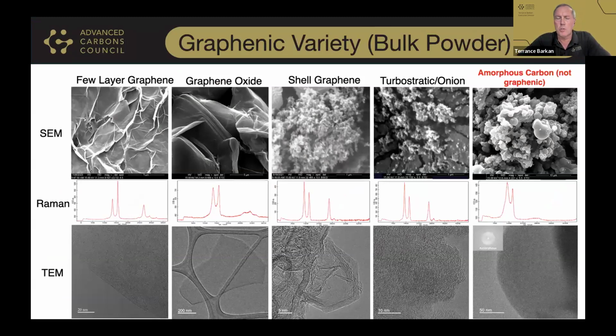And often when people hear the term graphene, they may not be entirely familiar with the fact that this is more like a family of materials rather than a singular specific material. Graphene can include sp2 bonded carbon that's in a single layer up to 10 carbon layers. On the left you have an example of a few layer graphene platelet. There's also a material referred to as graphene oxide, which has a high percentage of oxygen content, 30 to as much as 40% oxygen, which changes the behavior of the material significantly. Graphene, of course, is noted because it's highly electrically conductive, but graphene oxide is an electrical insulator because of the oxygen.